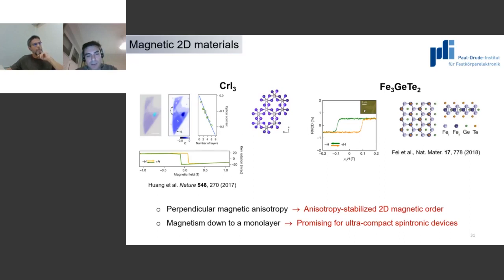Yeah, but in general, this perpendicular magnetic anisotropy is confirmed. For instance, here what I show is the MOKE measurement, the Kerr rotation, and the magnetic field is out of plane. So you only see this hysteresis if you do have spins out of plane, right? And the same is the case here. But you're right, it should be an Ising model, but it's not that easy. And there are also some systems, I think chromium bromide, the group from Max Planck, Stuart Parkin, they have been able to grow monolayer islands on epitaxial graphene by MBE, and interestingly, for this material system at very low temperatures, the XY model seems to describe the results better, meaning in-plane magnetization.